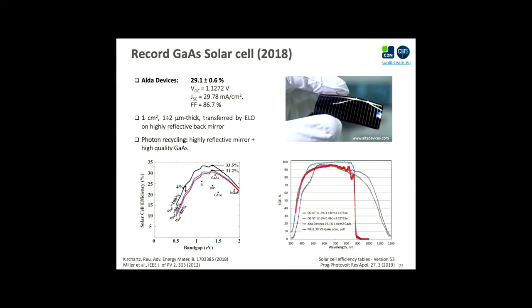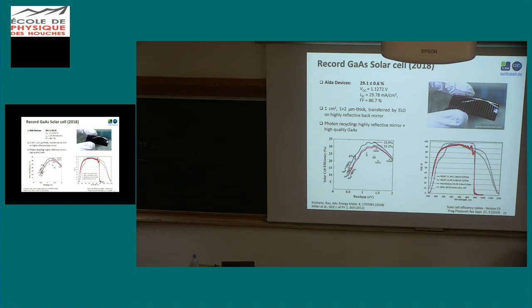So this is the record I was mentioning before from Alta. 29.1%, it's over 1 square centimeter, in the range of 1 or 2 micron, we don't know actually. And this cell was transferred, so you first grow your crystal or epilayer on a gallium arsenide substrate, and then you manage to remove it from the substrate and replace the substrate with a highly reflective back mirror. By doing so, you can, of course, gain a double pass absorption. Stefan will talk extensively about these problems of light trapping. So we have, in principle, a double pass absorption because this light is reflected at least once.